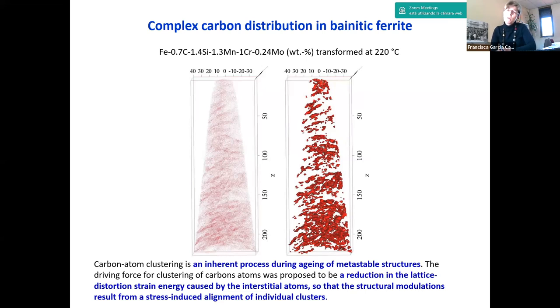We saw tetragonality related to carbon clustering as in martensite, but we didn't say how much carbon supersaturation there is in this bainitic structure. Carbon clustering and tetragonality are related to carbon supersaturated ferrite, but how much carbon supersaturation do we have? That's the last thing that I want to explain to you.